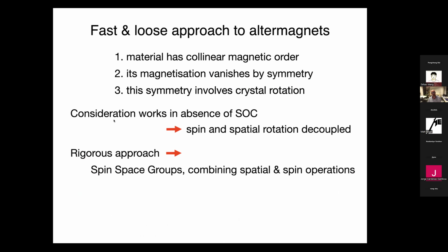Okay, so here is what I call the fast and loose approach to altermagnets. Collinear magnetic order, magnetization vanishes by symmetry. This symmetry involves a crystal rotation. And this consideration works in the absence of spin-orbit coupling. It's obvious that if you have spin-orbit coupling, you cannot consider the rotation of spin and the spatial rotation independently. These are intrinsically coupled. And the symmetries that I talked about so far actually were decoupled spin and spatial rotation symmetries. And if you want to do this not in a hand-waving way, but rigorously, you will have to consider spin groups and combine these spatial and spin symmetry operations.